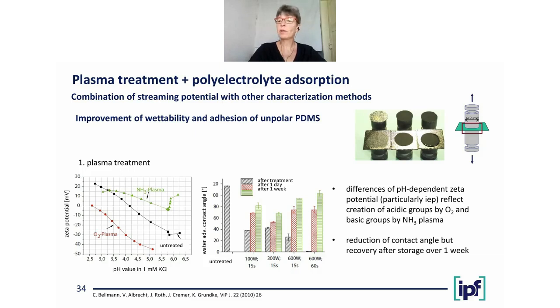Another example, also for the microelectronics industry, was at the very end of the production line, the housing of the microchips. There were problems that the PDMS housings did not attach properly to the chips, and that's why we tried to improve the adhesion of PDMS, the polydimethylsiloxane, on metal surfaces. The method of choice was a plasma treatment. This also helped to reduce the contact angle and to improve the adhesion.